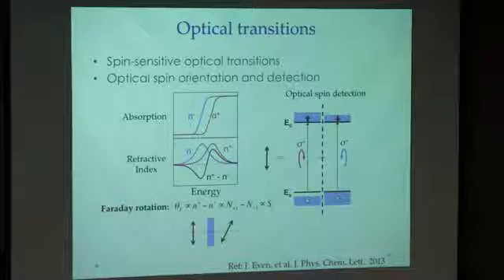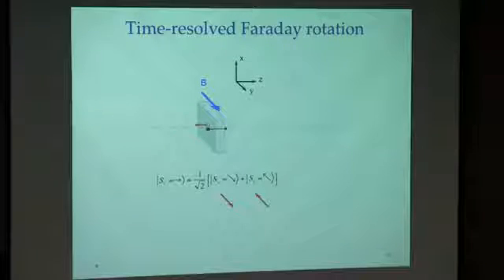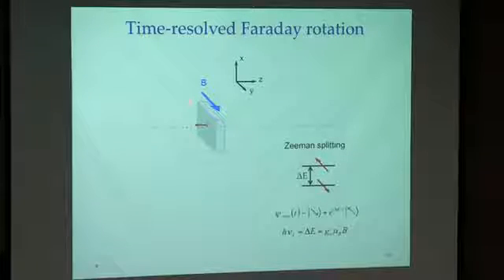The phenomenon is that with a linearly polarized light, you can have a rotation of the polarization plane by a small angle, and that small angle is proportional to that difference here, and also proportional to the spin polarization in the conduction and the valence band. We do this measurement by excitation and probe in an ultrafast optics measurement. Here's how it works. With a right circularly polarized pulse, we create spin polarized electrons and holes. If we only look at one spin species, say spin half carriers, then it's a superposition of spin up and spin down along the magnetic field direction.